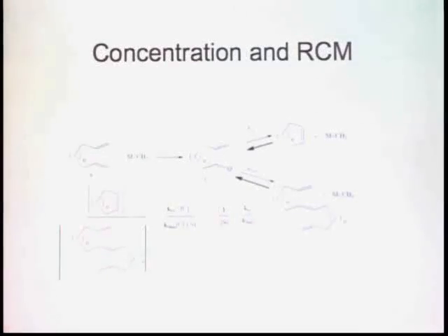So for example, norbornene goes completely to polymer. You cannot take it back to norbornene again because of 25 kilocalories per mole. So you have to be able to control the reaction by just concentration. And some rings you can't close. We fail in many cases. So basically it could be controlled by adjusting the concentration of the solution. Yeah, right. Mostly, yeah.